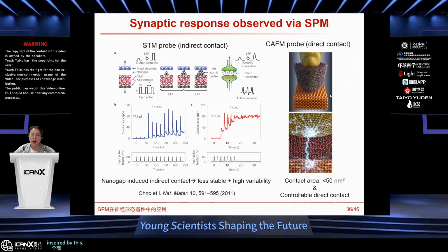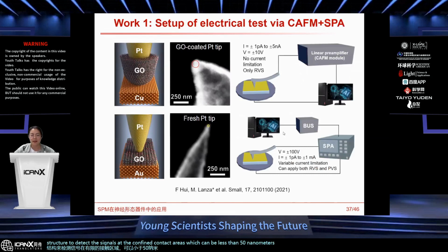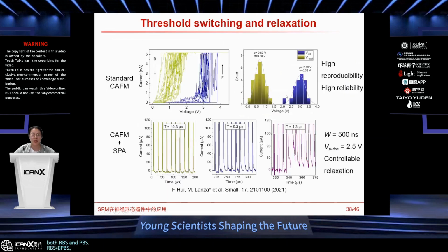Inspired by this work, we considered using C-AFM because it has a controllable direct contact between the tip and the samples, and we can use this kind of structure to detect the signals at confined contact areas, which can be less than 50 nanometer square. As I introduced in my previous slide, we connect the C-AFM with the SPA to extend its current and voltage ranges, and can also apply both RVS and PVS. And here I show the data that we collected.